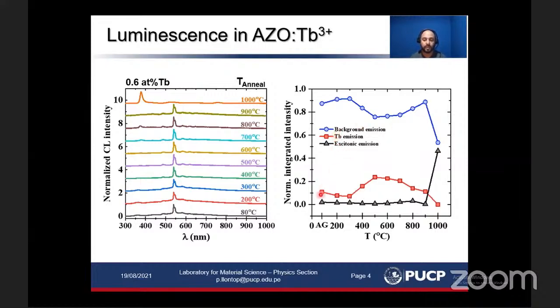So first the background emission, which covers the whole spectral range. The terbium related emission, which covers just the peaks, and the excitonic emission, which is centered at 380 nanometers. And at 300 degrees of annealing temperature, we can see that the terbium related emission starts to increase until 500 degrees. So we believe in this range there is an optical activation occurring due to these thermal treatments. So there is an improvement of the terbium related emission.